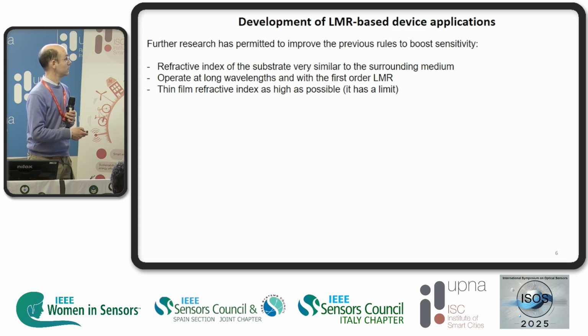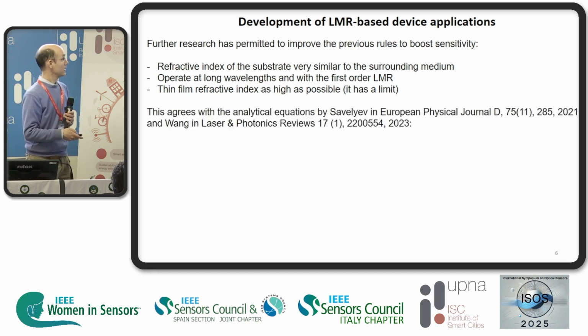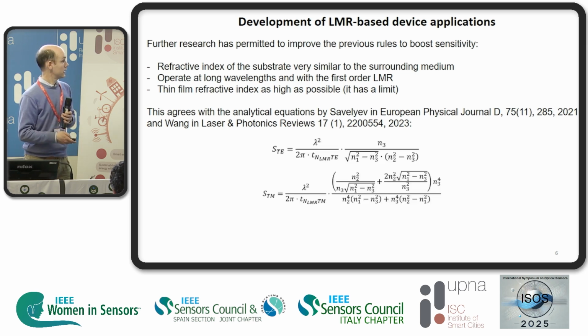The thin film refractive index as high as possible, though there is a limit, it saturates for very high values. And all this agrees with analytical equations obtained by Savelyev in this journal and by Wang more recently in this other work. Here is, for the first time, the equations for TE and TM, analytical equations for sensitivity. And it is interesting to observe something that was observed empirically during the last years, that the sensitivity is proportional to the square of the wavelength.